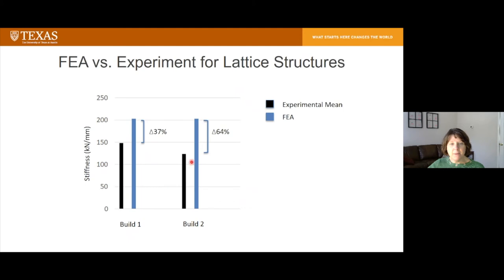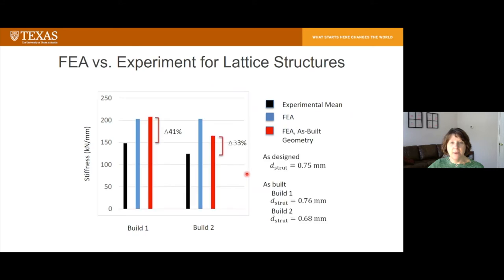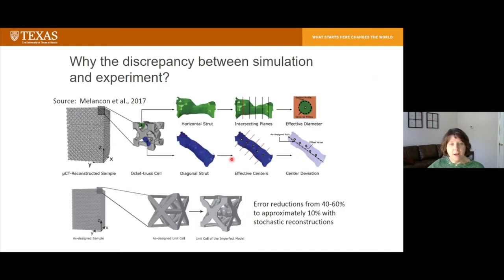So if we look at the experimental mean in black versus our finite element predictions, they're off by as much as 60%. And the experimental results are much less stiff in this case than we expected them to be. In many cases in additive manufacturing, the as designed dimensions are not the same as the as built dimensions. So if we correct for that, which we did here, our errors get a little bit better, but they're still 30 to 40%. And that's not particularly good. So what could be causing that?